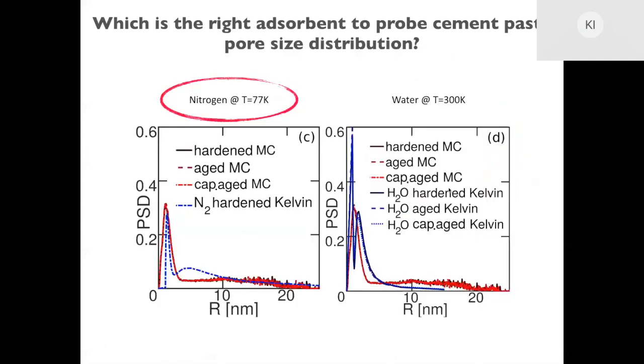So the next point is that from adsorption desorption curves, we are able to determine the pore size distribution. So a lot of times in the literature, there are results of pore size distribution that are reported using water as an adsorbent. And this is basically, as you can see here, from the comparison between the simulations and the experiments, because we can probe the pore space in the simulations with a Monte Carlo technique. So basically, we take a sphere and we can really probe the geometric space, but we can also compute the pore size distribution from the isotherms, like they do in experiments, and compare the two and see which one is giving the best results. So clearly, the nitrogen is the right